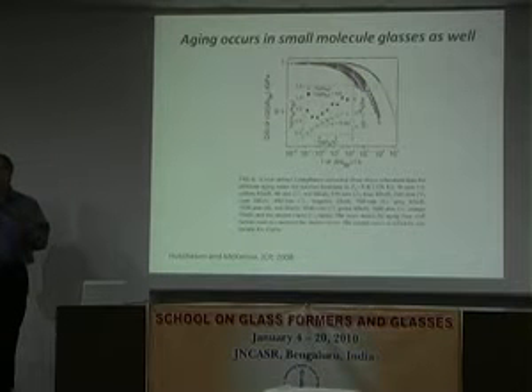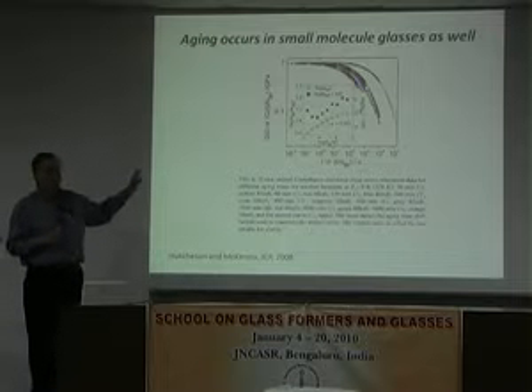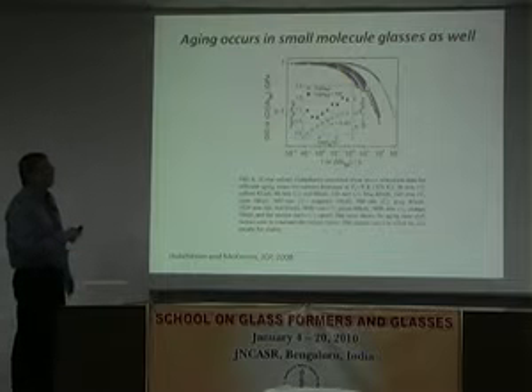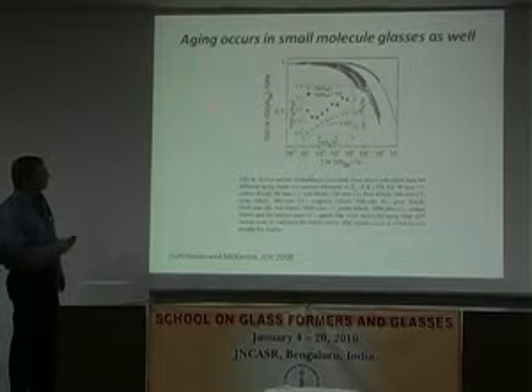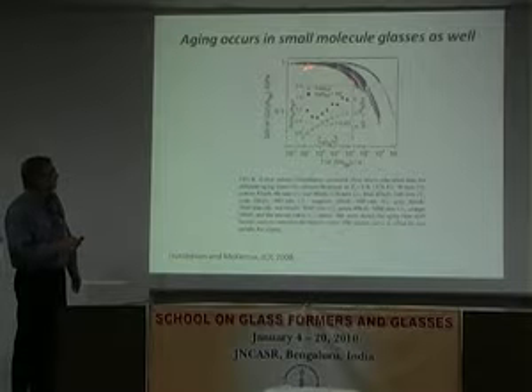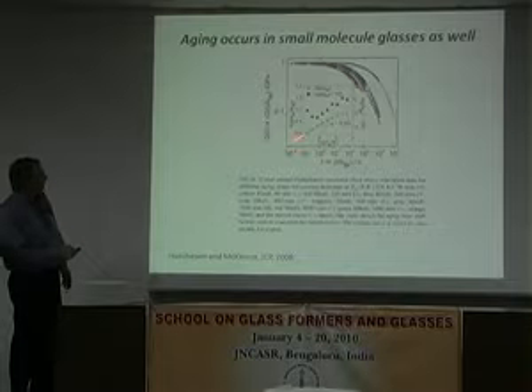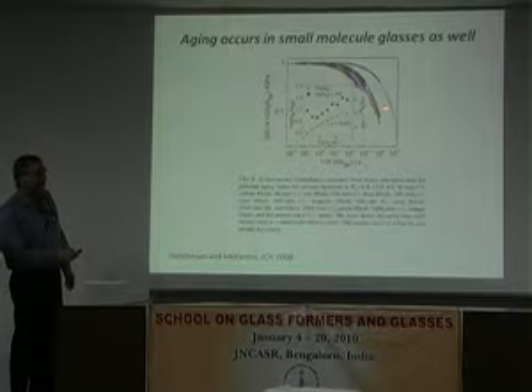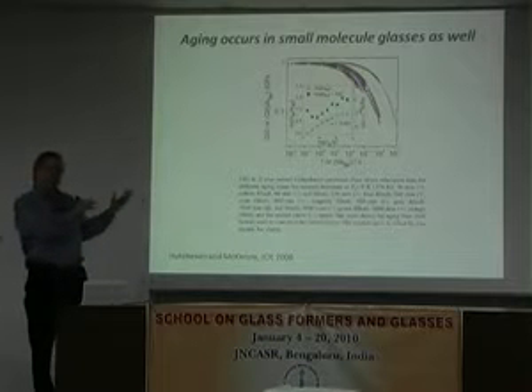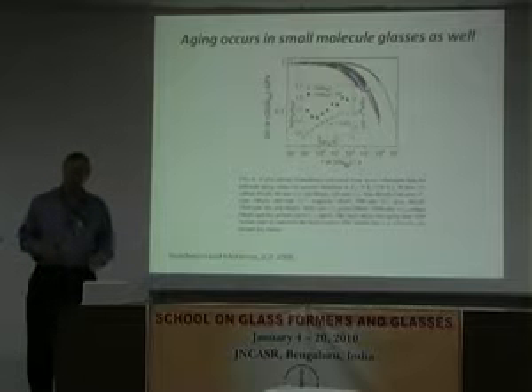And then I just want to point out that, of course, not the humidity behavior because we haven't done it, but this kind of aging behavior is well known in small molecule glasses as well, and this just shows some results we have from sucrose benzoate. So you get aging time superposition to create a master curve, with a slope, and we find that it gets to equilibrium when we're close enough to the glass transition. So all glass formers show this kind of behavior when we're in the right conditions. So it's not unique to polymers by any stretch.